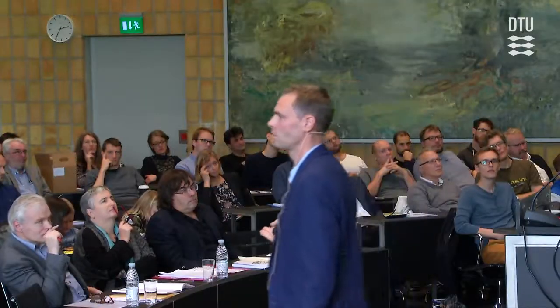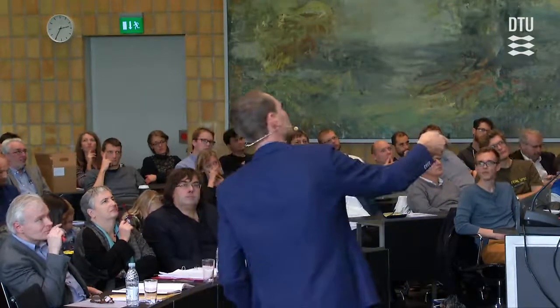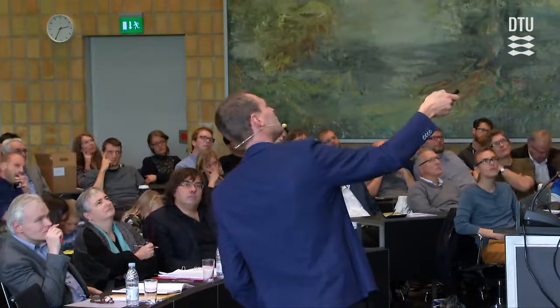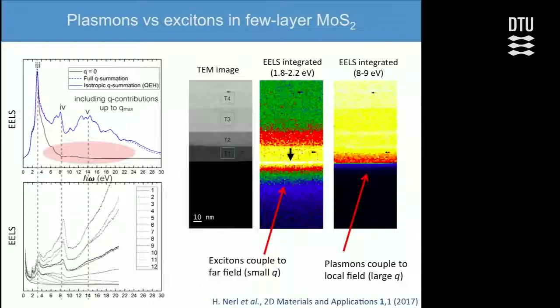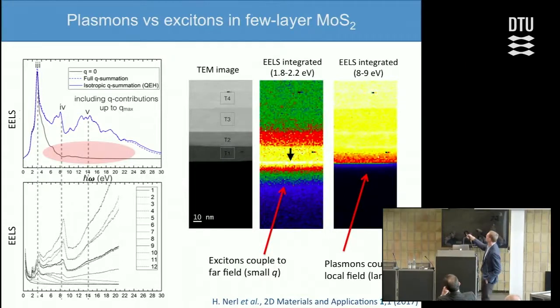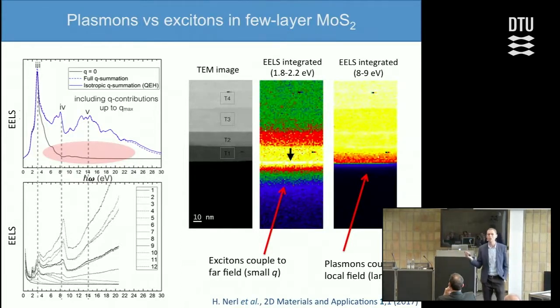If we look at the plasmons instead, by integrating the EELS spectrum over this peak up here, then we see a much sharper transition from the sample into the vacuum region. That's because we can only excite plasmons by the high Q values, by the rapid variations of the electron beam. This is again very different from the three-dimensional case.